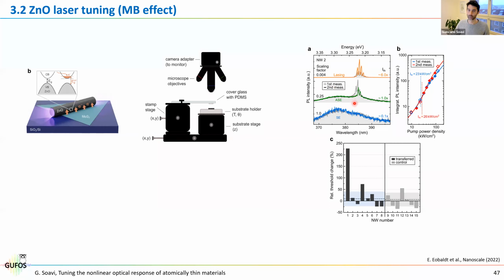So first of all, without the TMD, we take the zinc oxide nanowire and we transfer it from one substrate to the other, and we look at the lasing properties. So this is the typical lasing characteristic. When the pump is low, you only have spontaneous emission. As you increase the pump, you start seeing this amplified spontaneous emission. And then at large values over the lasing threshold, you have these very sharp lines.